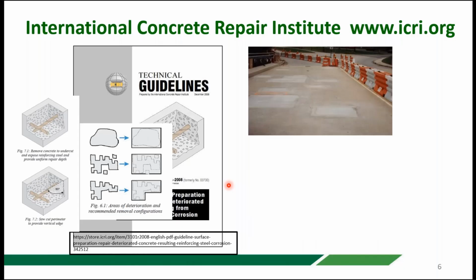If you do that, and this picture here in the top right corner shows some repairs done by Virginia DOT on a bridge deck just outside of Washington, D.C. And they've followed basically all of the recommendations of the ICRI guideline: good square cut edges, chipped around behind the bars, good quality repairs. And so if you follow those procedures, the repair itself will be fine.